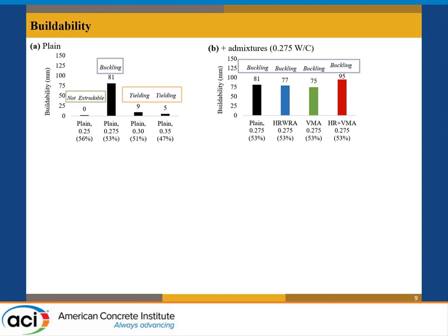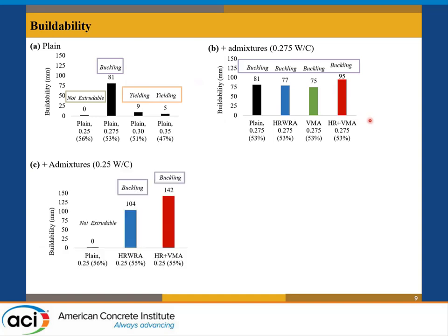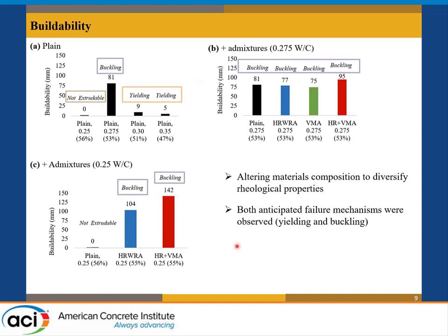If you look at systems with admixtures, you can start tailoring, improving, or diversifying the buildability — all of which demonstrate a buckling mechanism. Similarly, you can take an un-extrudable paste and design the material for buildability, but buckling becomes the dominant failure as you overcome extrudability and yielding. Both failure mechanisms that we anticipated were observed, and we particularly focus on the buildability that resulted in buckling and its correlation with rheological properties.